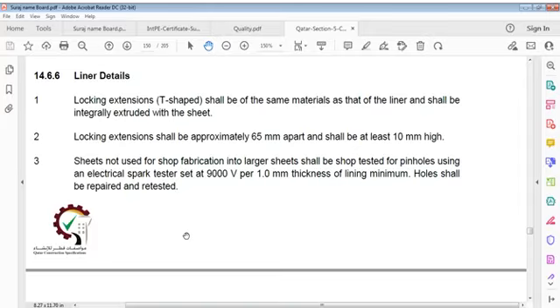This locking extension, which is T-shaped, shall be of same material as that of liner and shall be integrally extruded with sheet. Locking extensions shall be approximately 65 mm apart and at least 10 mm high. Sheets not used for shop fabrication into large sheet shall be shop tested for pinholes using an electrical spark tester set to 9000 volt per 1 mm thickness of lining minimum. The holes shall be repaired and